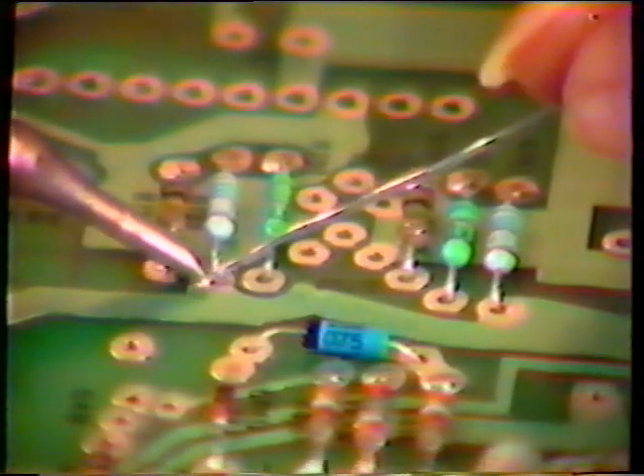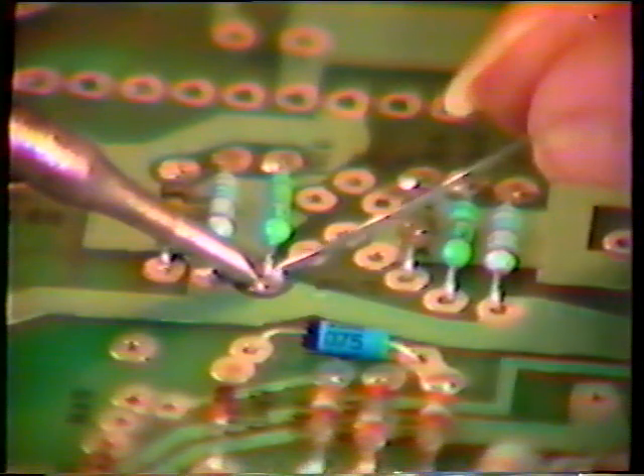The other extreme is where the rosin core solder doesn't completely cover the joint area. Molten solder must flow freely over the metal surface for good wetting action. With too little solder, a good solder-to-metal bond cannot take place. Insufficient solder can cause the connection to rupture due to stress, vibration, and fatigue, leaving the joint non-functional. It's important to learn to apply the correct amount of solder and determine whether a joint meets quality and reliability standards, and to recognize faulty connections so you can correct them.